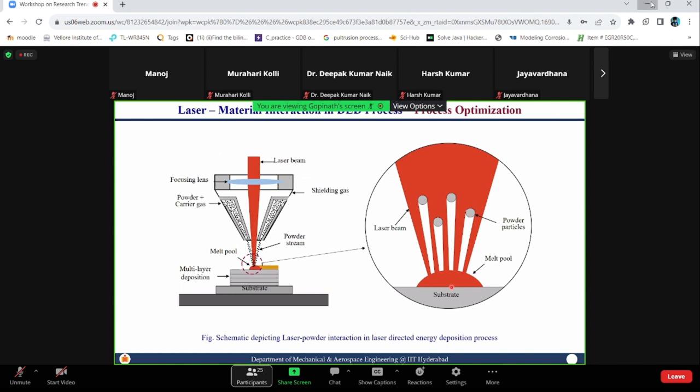Right? Parallelly, earlier it was in 3D heat conduction because it was conducting heat in every direction into the substrate. Now it has to be 2D. It has to conduct through this fine wall. Because of this heat accumulation effect, as well as poor conduction, the beads will either start to overflow, which results in geometrical inaccuracies as you keep building up this wall. Now, let us see, is it true? Does it really happen in reality?